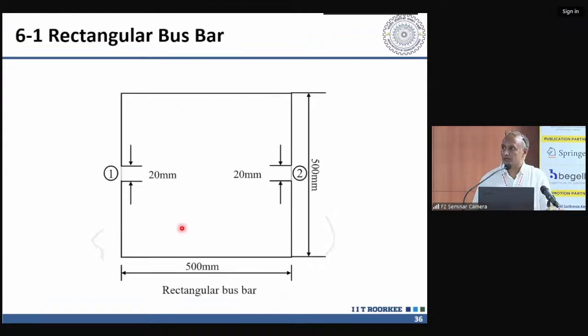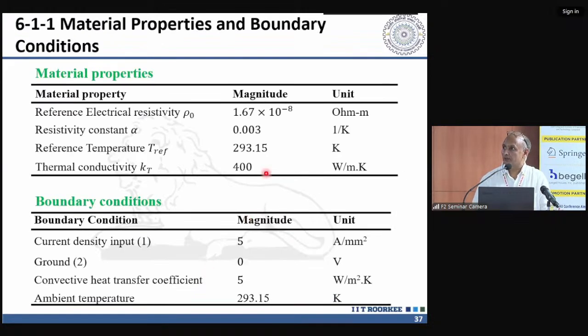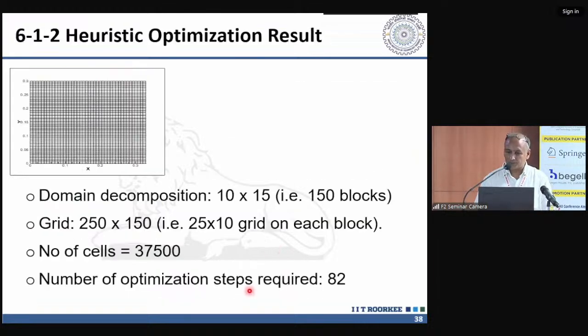We started with a simple rectangular bus bar with two ports, one input port and a ground port, 500 mm square. These were the reference properties of resistivity and thermal conductivity, which we assume to be constant. For copper, in our range of interest, that's 273 Kelvin to 373 Kelvin, the conductivity of copper remains more or less constant. So in our thermal problem, we have assumed constant thermal conductivity. For the current density input, we took a few different options available. Similarly, we also varied the convective transfer coefficient.